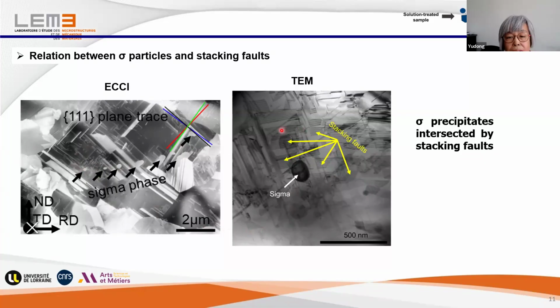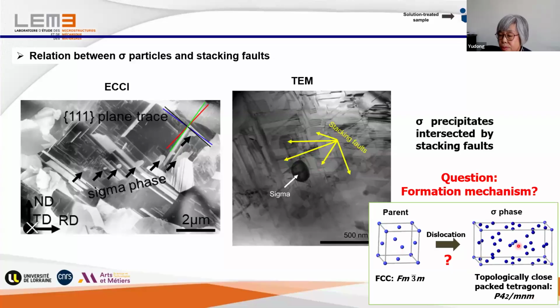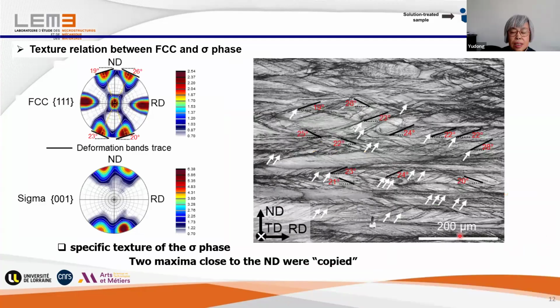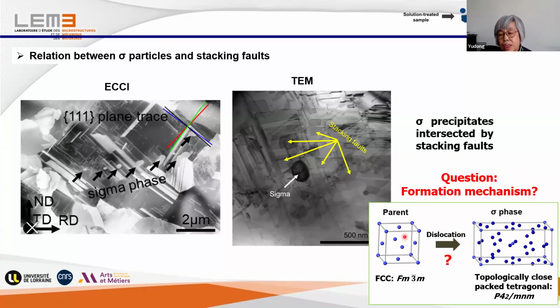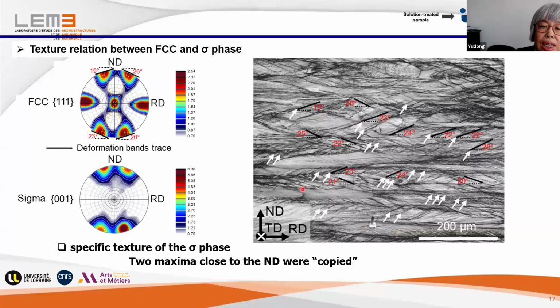And if we have a closer look with TEM, you see here is one sigma particle and around it it is full of stacking faults. And so the question is, from this structure to this structure, how do the stacking faults and dislocations help this atomic process, because the transformation is really ultra rapid, not normal. And then to really know the atomic passage from here to here, we need to have a correlation between these two structures.